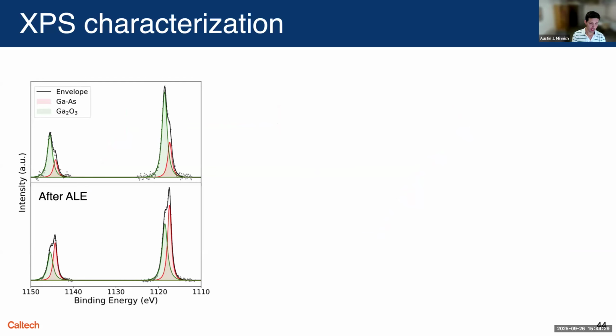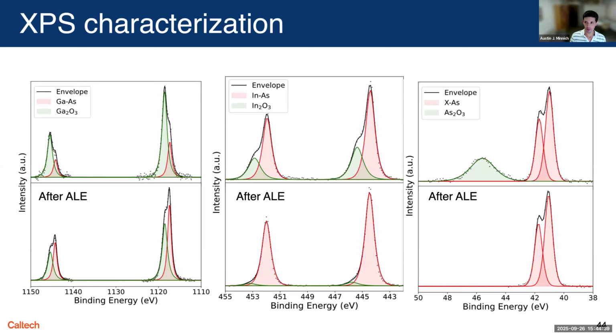All right, and then as a last check of whether we understand what's happening, this is the XPS for gallium and indium and arsenic. If you look first at the center and right images, just like I showed before in the plots from the reference, you see the green shaded region, which is the oxides, is essentially gone in the bottom panels, which is after ALE. If you compare vertically, top to bottom. Returning to the left image, which is the gallium and gallium oxides, we can see they're significantly reduced, as evidenced by the green area. Compare the top and bottom. They're not gone completely though, which is actually expected just because the gallium oxides are generally more stable than the indium or arsenic oxides. But overall, we've removed a significant amount of the oxygen as evidenced by XPS.